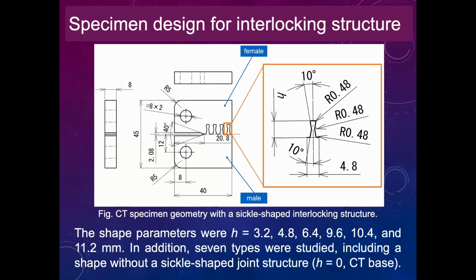In order to discuss the effect of the geometry of the sickle joints on the fracture toughness, the height of the sickle joint as the shape parameter H was set to 3.2, 4.0, 4.8, 6.4, 9.6, 10.4, and 11.2 millimeters. We also prepared a CT specimen with H equals 0, which consists only of the base material.